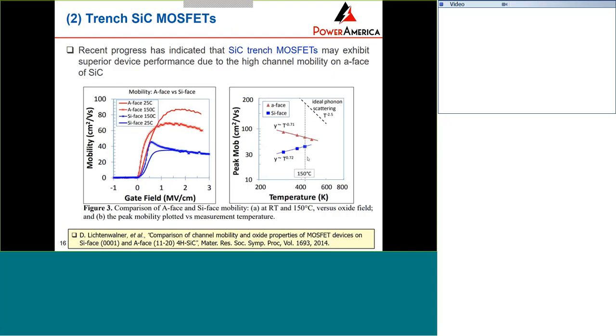One problem for the planar MOSFET is the low channel mobility, so you have to operate the devices at a fairly high gate electric field to fully turn on the device. To solve that issue, people developed the trench MOSFET, because the study has shown that the silicon carbide MOS channel mobility on the a-face is higher than the mobility on the silicon face, as shown in the left figure. It shows the mobility versus the gate field at room temperature and high temperature for devices made on the a-face and the silicon face.